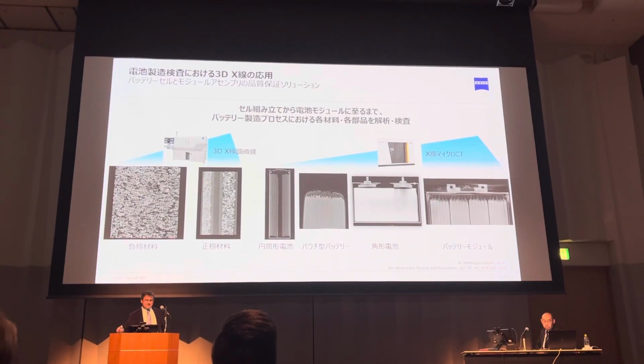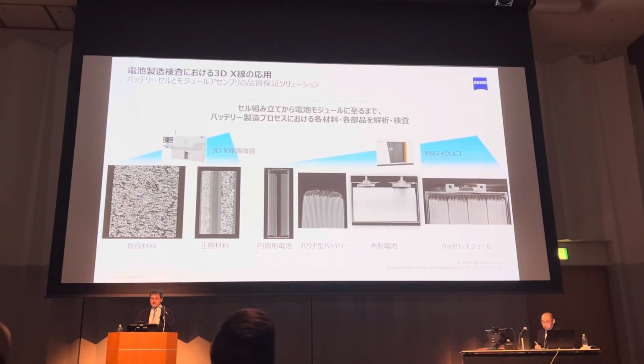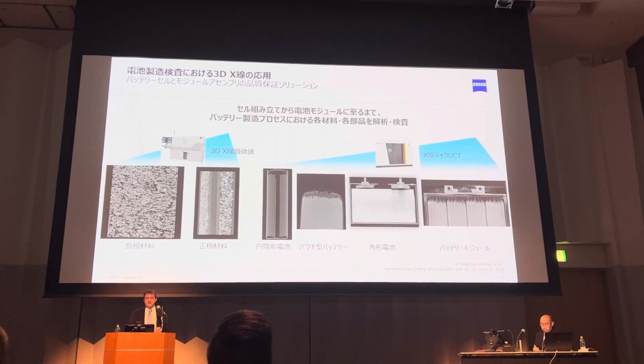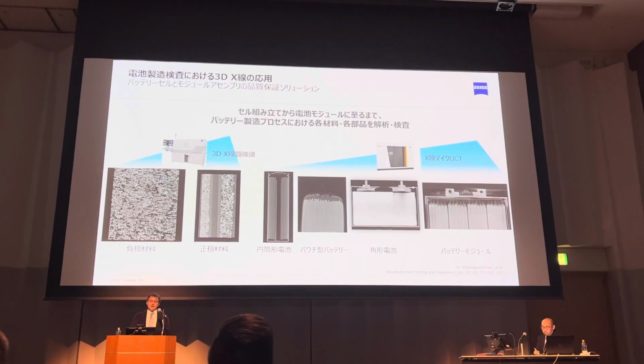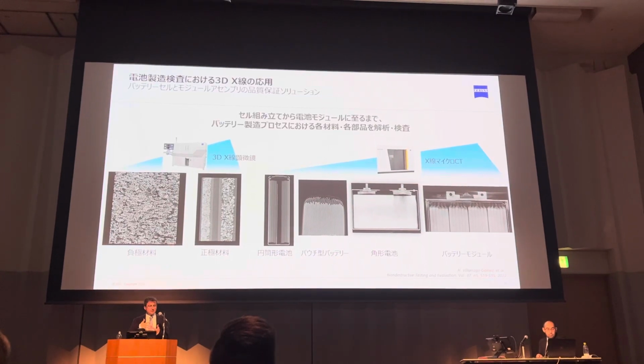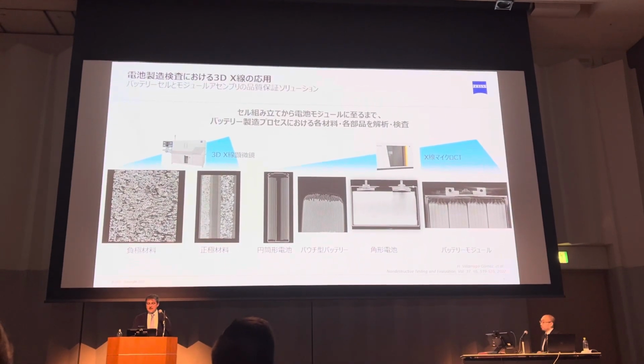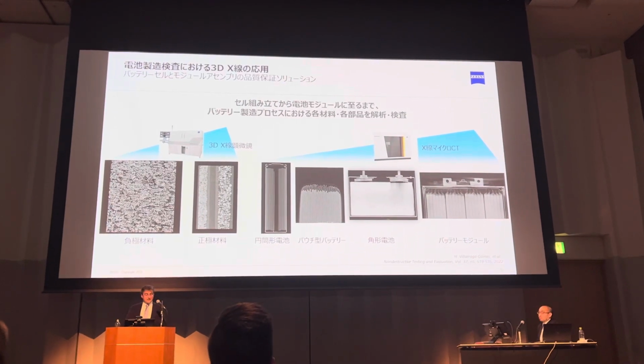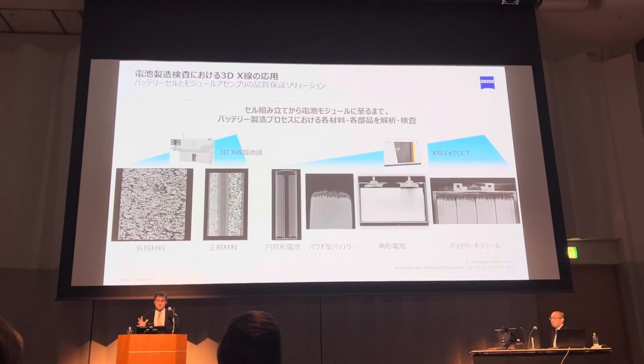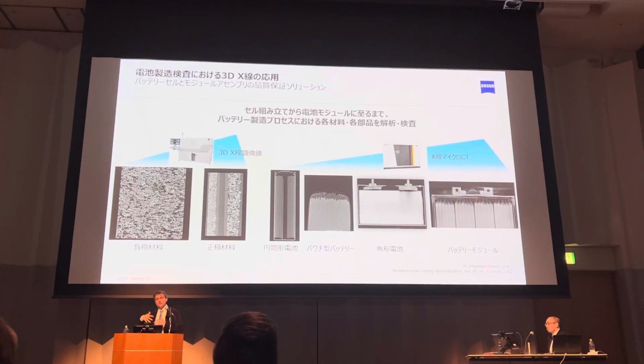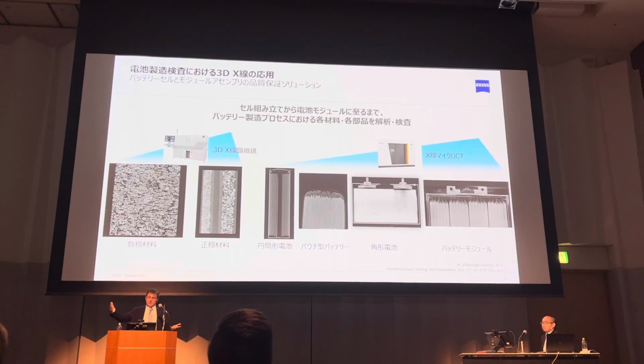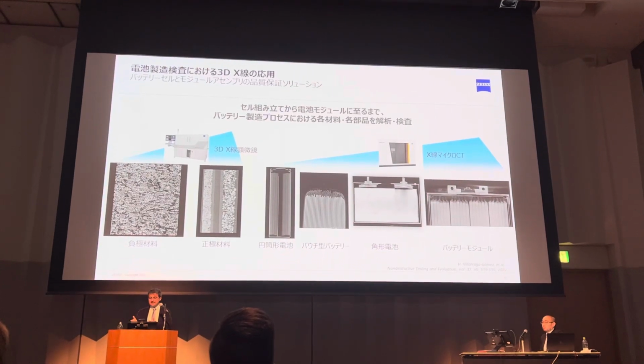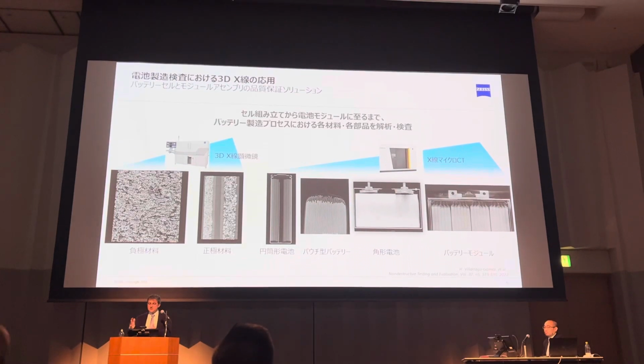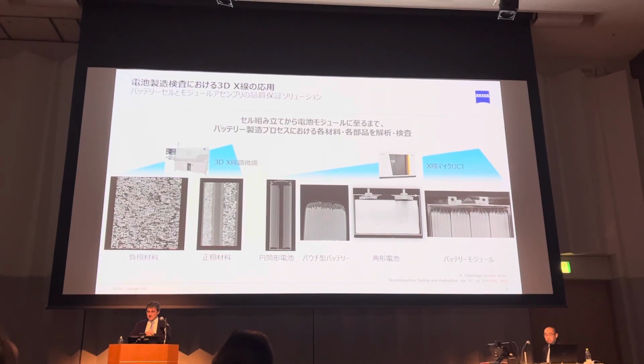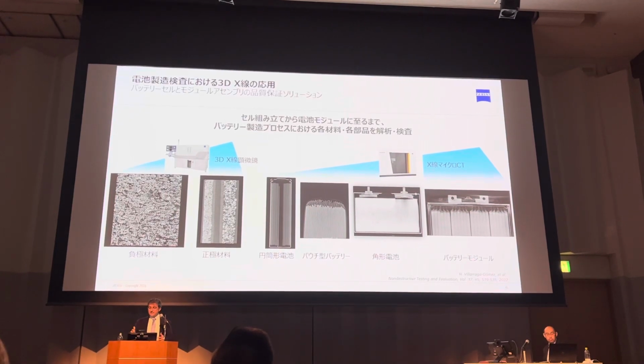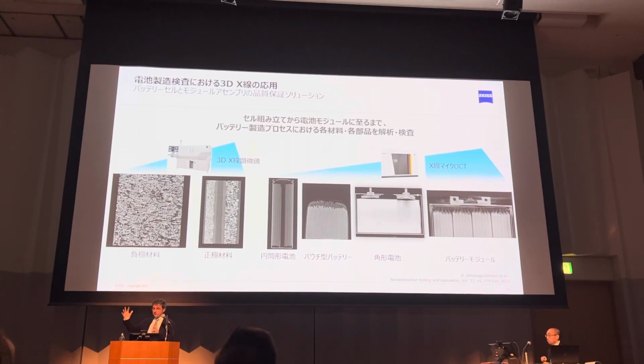Now, I have been talking about X-ray microscopy and X-ray computed tomography. X-ray microscopy, as is explained in the plot, is really great to study some of the small details inside of the battery, including materials from the electrodes. And now, if you want to scan larger batteries, there is a compromise. You probably won't be able to do with low energy X-rays, and you will have to raise the kV from 160 to maybe 220 and 450, but then the resolution is compromised. However, you still see some details that you might be interested in the large shape of the battery. So with X-ray computed tomography, you can even see the full battery pack.